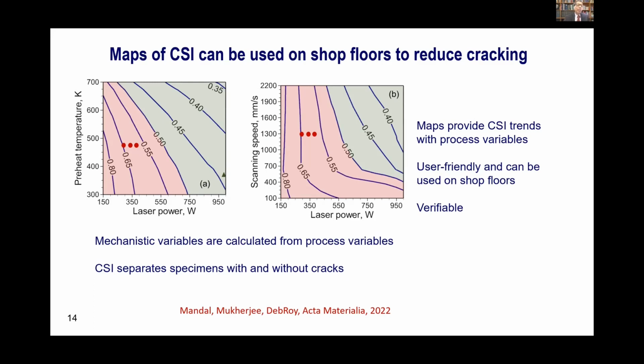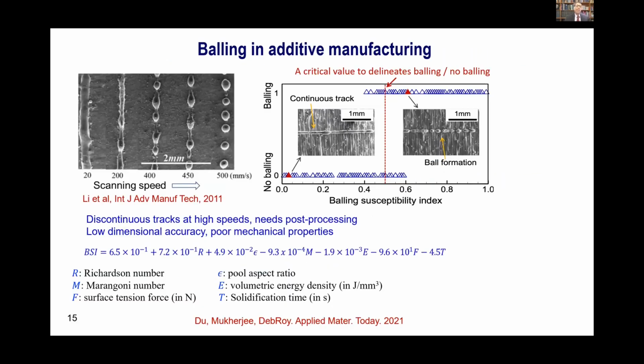And we can even convert the CSI to maps like laser power, preheat temperature, scanning speed, and plot contours of the crack susceptibility index. The green areas are good. The areas with higher cracking susceptibility index ranging from 0.5 to about 1, they are red zones. They are not good. We have verified those with experimental data to show that these maps are reliable and therefore they can be used on the shop floor. Another persistent problem is surface roughness.